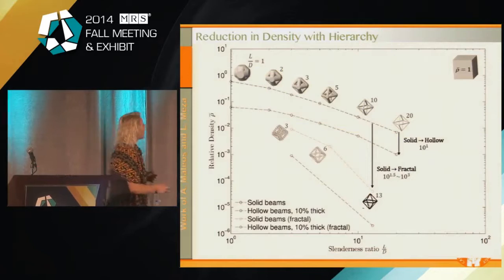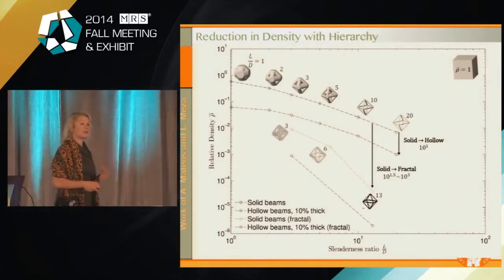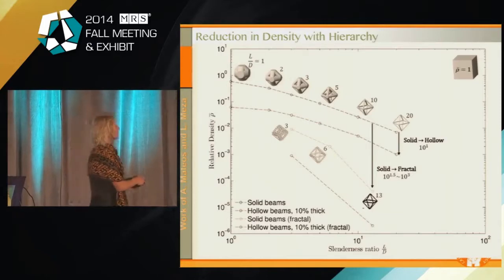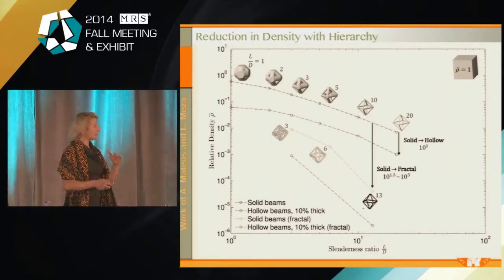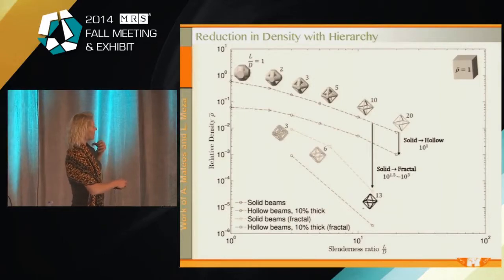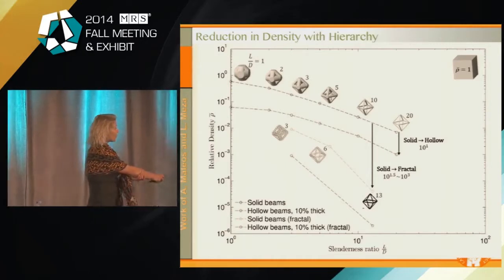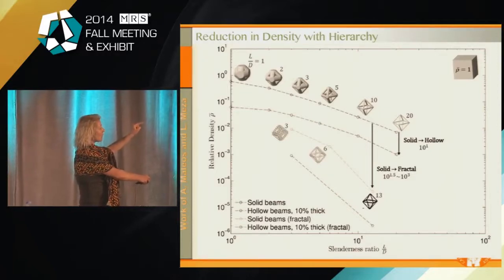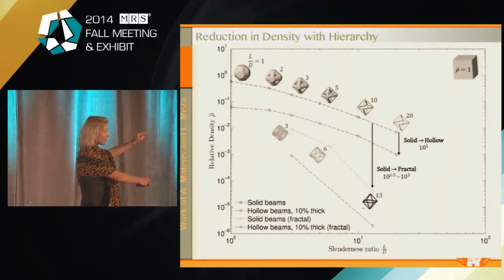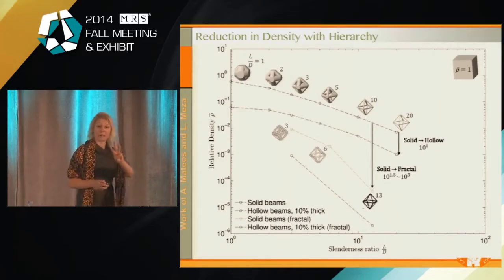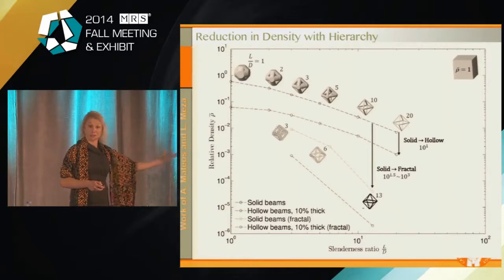Now, just to show you how much reduction in density we can expect with both hierarchy and making them hollow. If you take a monolithic cube of a material, and then you start taking away that material by changing the slenderness ratio, and what I mean by that is the length over the diameter. The slenderness ratio in a structure like this, for example, is 20, and here it's just 1, right? You can already hit about 2 orders of magnitude just by going slender. Now, if you hollow out each beam, you're able to get another order of magnitude. So just going from a monolithic cube to about 20 slenderness ratio and then hollowing out the tubes, you can lose 3 orders of magnitude in density. That's like going from the Great Pyramid of Giza to the Eiffel Tower, right?